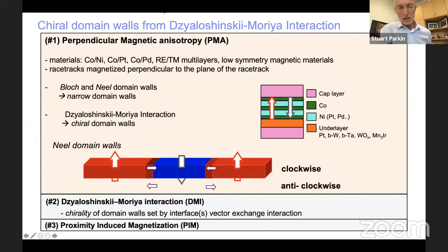And related to that, then, at that interface is another very interesting interaction, where there is a proximity-induced magnetization. The cobalt layer causes a moment to be developed in the platinum layer. This is an enormous moment. So typical racetracks, which are shown here, would consist of only 2 cobalt layers separated by 1 nickel layer. The cartoon shows more layers, but typically we'd only have 2 cobalt layers separated by 1 nickel layer. Then 50% of the magnetization of that cobalt-nickel-cobalt sandwich would be developed in the platinum underlayer. It's a very important effect.